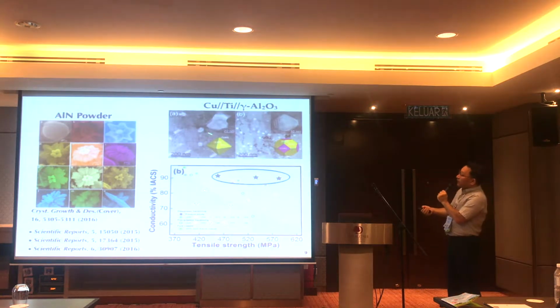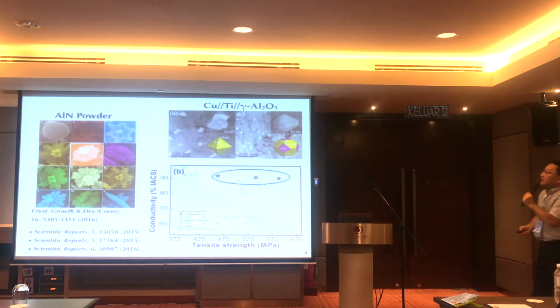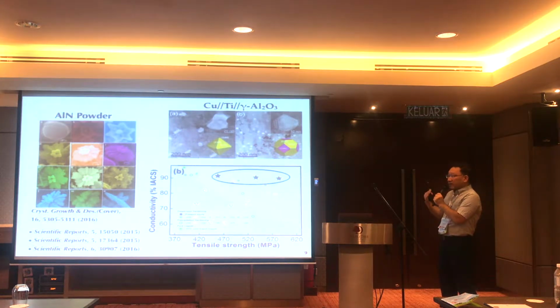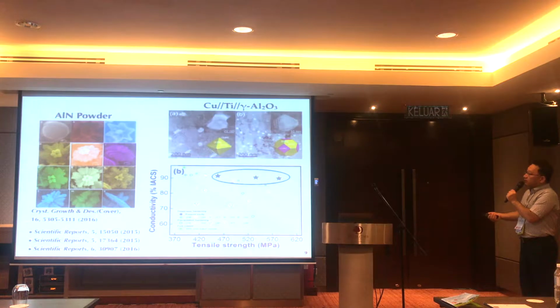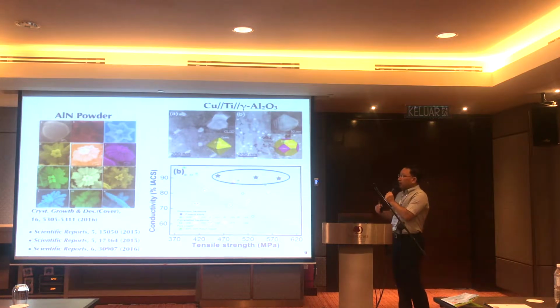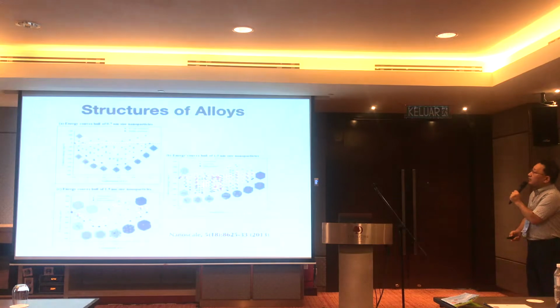Then what happened is that without titanium, we figured out that gamma alumina looks like that. Very fuzzy type of topology, as experimentally observed. This is the computational prediction. But if you add a little amount of titanium, the topology completely changes to a spherical shape. In mechanical engineering, once the dispersed particle is spherical, it is very good for mechanical strength. Also, this spherical shape does not block electronic scattering, electronic propagation, which means that electric conductivity is not degraded significantly. So we achieved that by combining experimental measurement and computational predictions. We got the best performance in the world. This performance has never been achieved before. So this is a good example of how computational prediction and experimental validation can achieve good performance.